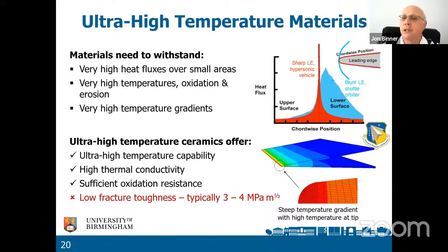And you can see the consequences in terms of the heat flux. You have a much higher heat flux with the hypersonic vehicle, but you've also got a much, much narrower heat flux in terms of the position on the chord where the material actually sees the full temperature. And that then translates into the lower diagrams, which is the sharp leading edge. And you can see how it's really only the very, very front edge which gets hot. And then the blow up of that shows that even within that narrow band, it's really right at the tip that you get the extremely high temperatures. So we've got extremely high temperature gradients and very high temperatures.